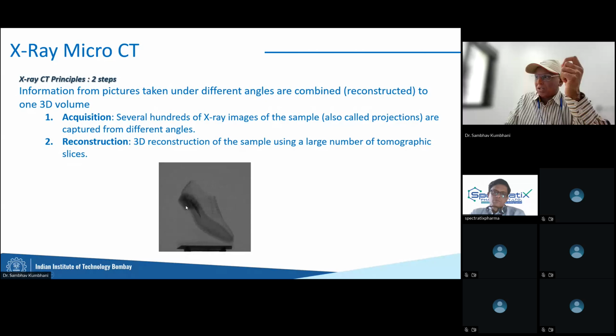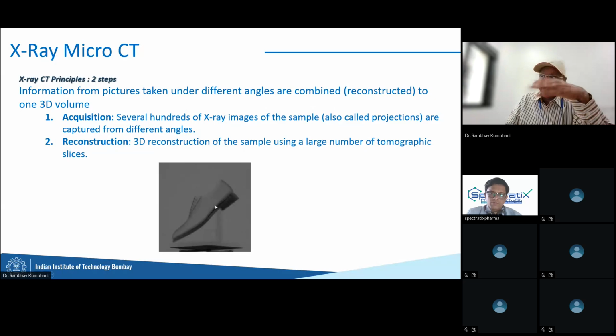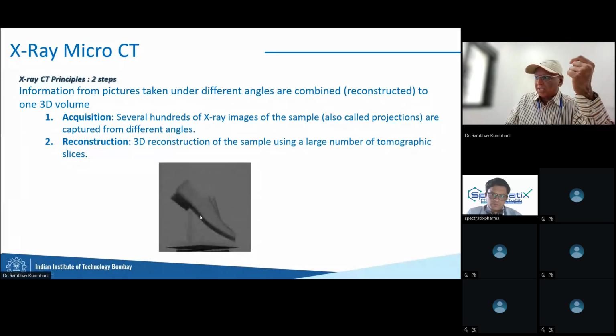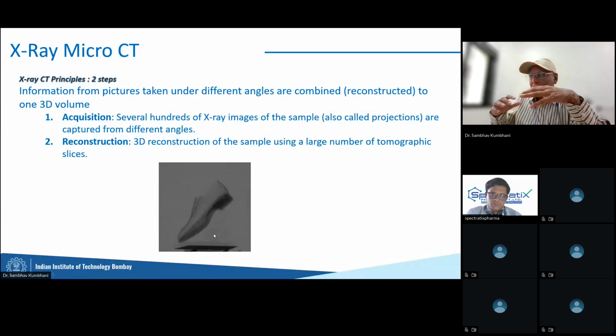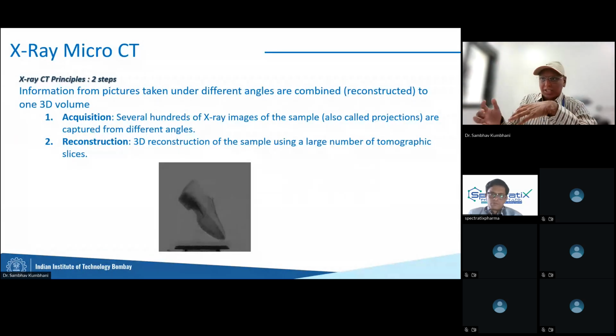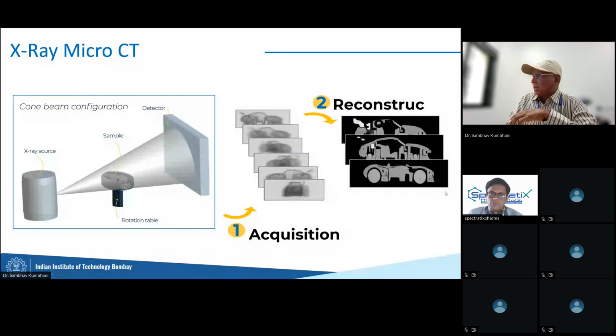It is different because the rubber sole is rubber, and the top part of the shoe is fabric. Fabric is very different from rubber. It interacts very differently with X-rays, and the lace is also a very different material. So all different materials will have a very different shade when you do a CT. Layered samples like the ones we are talking about would show up as very clean layers in a CT. Even in a car example, it is very obvious.